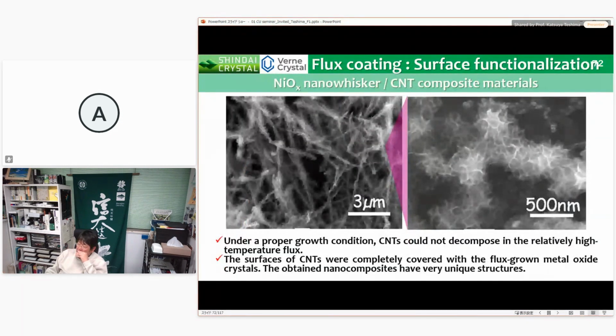These are the NIOX nano-whisker CNT composites. Under proper growth conditions, CNTs couldn't decompose in the relatively high temperature flux. As a result, the surfaces of CNTs were completely covered with the flux-grown metal oxide crystals, like these pictures.